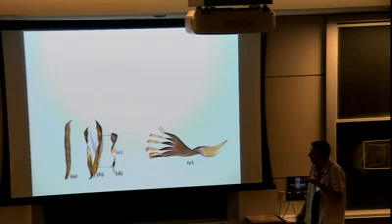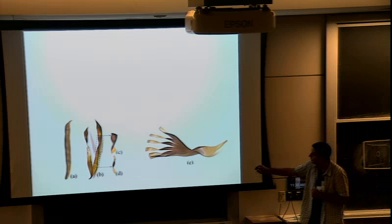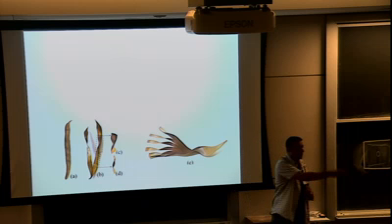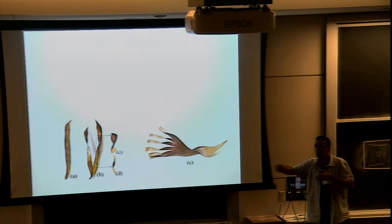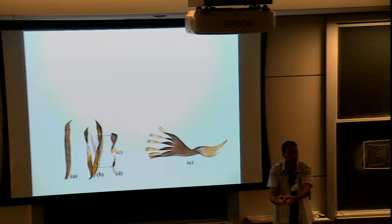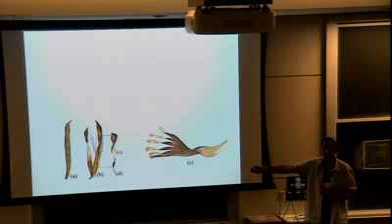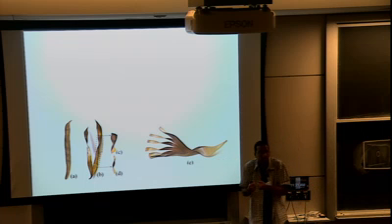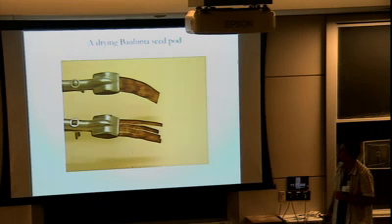Now, there's one way of figuring out if things are frustrated, and that's to cut them up. It's a bit destructive, but it's very insightful. So you take the seed pod, and you're not sure if it is under a state of residual stress or not, and you insert notches. And if the sheet continues to deform after you added these degrees of freedom, it can actually deform in ways it could not before, as it has here, then it tells you that the contiguous portion was straining itself, was in a state of self-stress, if you'd like, in a residual stressed state.